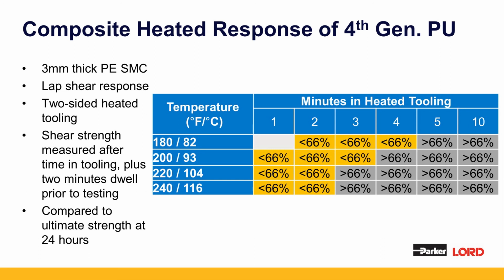So overall, the fourth generation structural polyurethane has a good response to heated tooling, and it's really a low heated tooling. Again, this goes back to the fact that sometimes tooling isn't sufficiently heated at the beginning of production, or there may be cool spots in the heating and the tooling itself leading to quality problems. In this case, the fourth generation polyurethane is a room temperature curing. So if the tooling doesn't achieve sufficient heat in one area, the product will still cure and we won't have a quality issue with the part. However, as you can see here, you can lower the tooling temperature and typically extend the life of it.